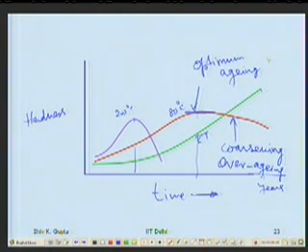After optimum aging, when the overaging is taking place, the fractional volume of the precipitate is not going to change. But here the fractional volume is changing, because the total amount of precipitate has not yet formed. It keeps on forming. Now, second thing, at higher temperature, the initial hardness is higher, because in the same time, more particles nucleate. Nucleation rate is higher. Second thing, the hardness maximum at the optimum is lower at higher temperature.